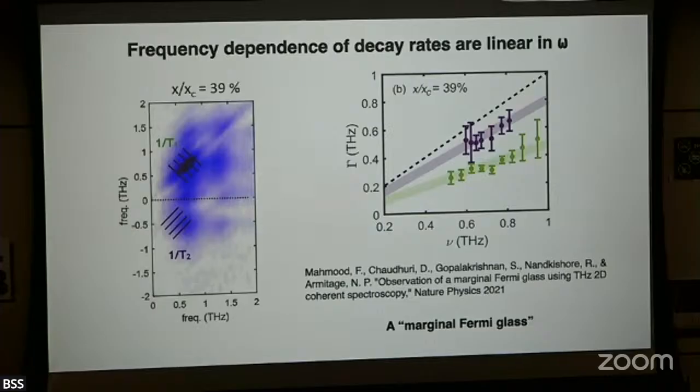Yeah, so they also have interesting temperature dependences. The 1 over T1 basically has no temperature dependence up to about 30 Kelvin, whereas 1 over T2 does. The temperature dependence is also such that these lines actually get a little bit narrower as you go up in temperature, right? So this is also an unusual thing. From that observation, we ruled out that the principal effect of this broadening was lattice interactions, so phonons basically coming along.